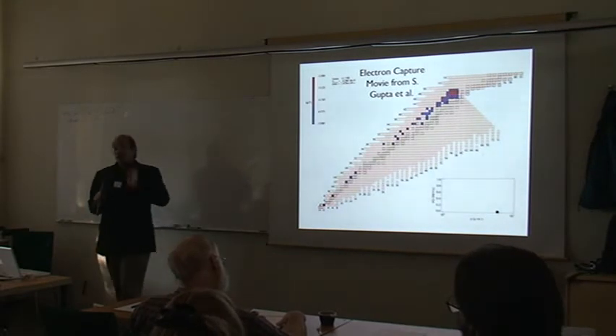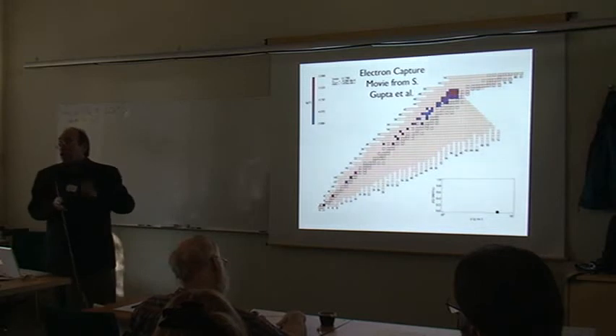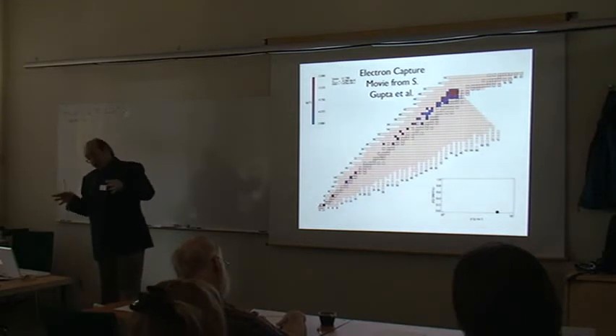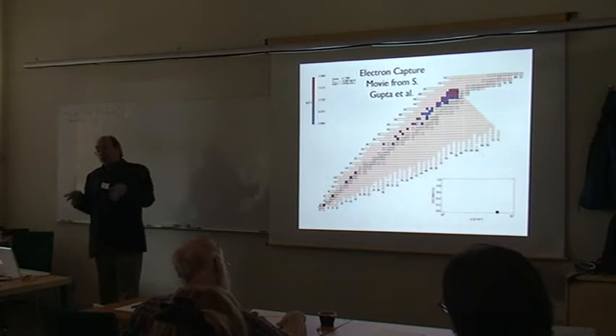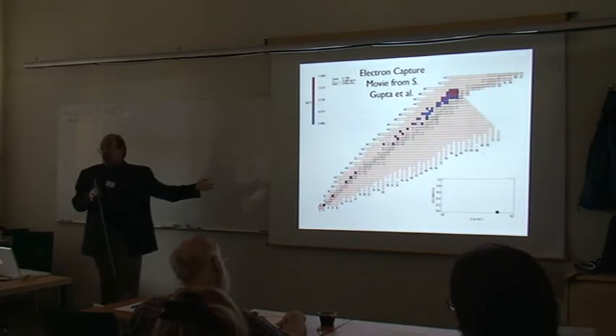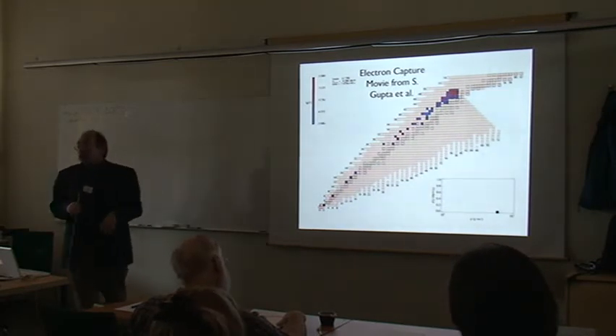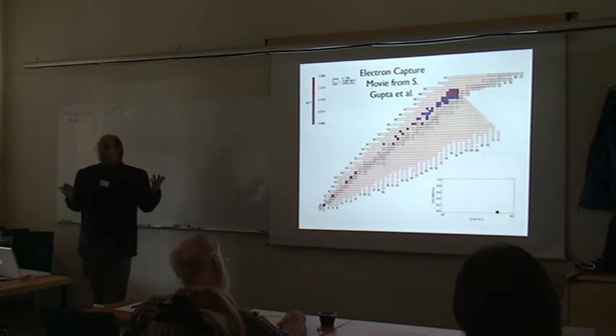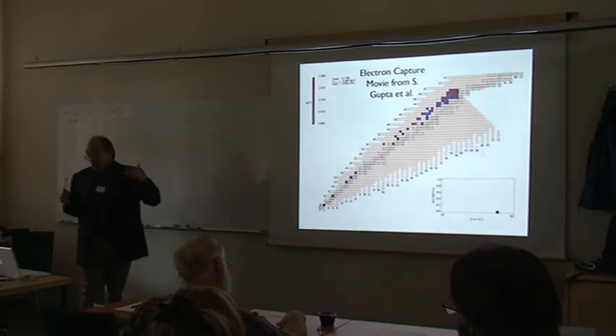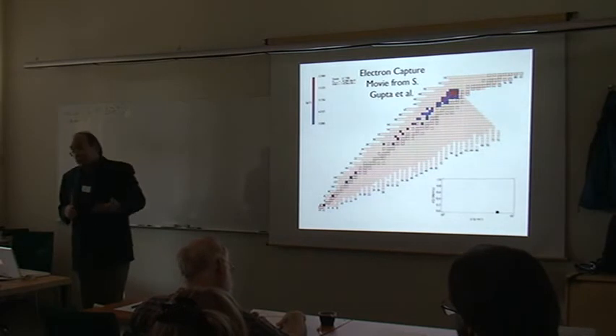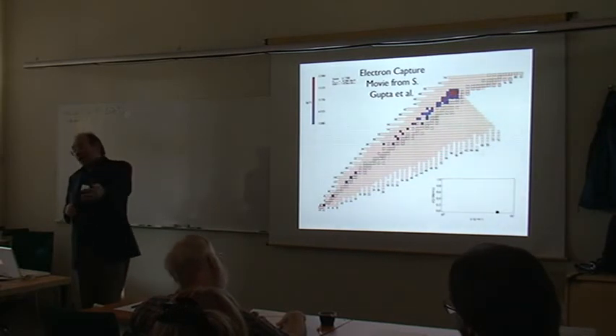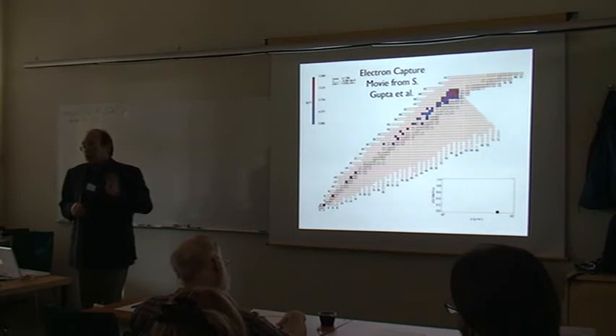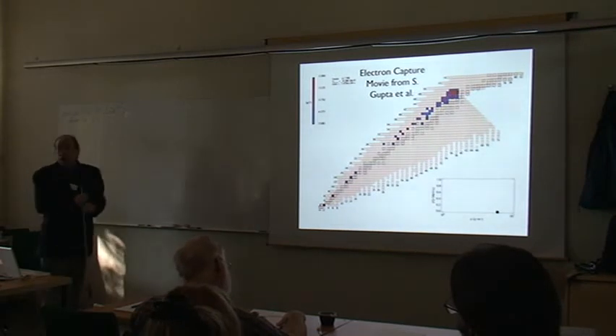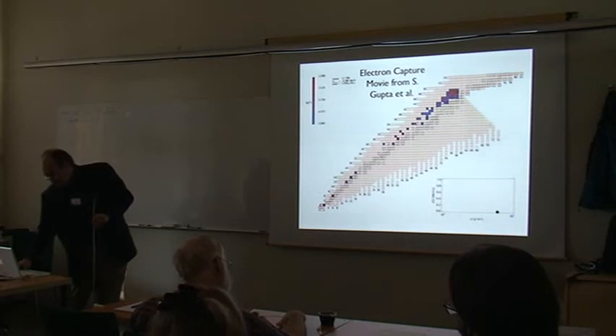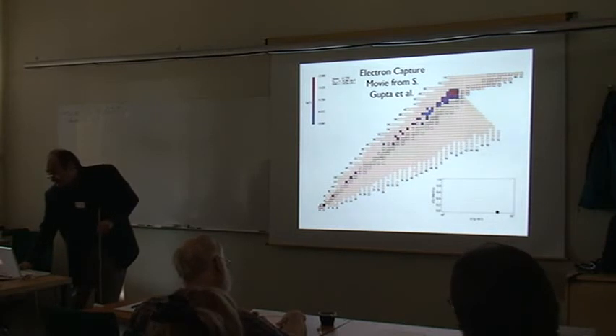Yeah, it is sensitive. It depends on how it burns. If you have the superburst, which is burning a lot of carbon, you get a very different ash than this rapid proton capture nucleosynthesis. And it can also depend on the conditions - if they're not as extreme, you don't burn all the way to mass number 100, you get lighter elements. So different simulations will give you different compositions, and that's certainly something one should explore more.